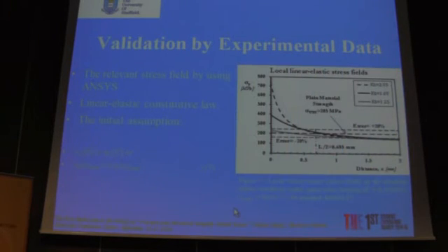From the linear elastic stress field in the vicinity of the notch, tested under quasi-static conditions for 6063T5, it is fully confirmed that the inherent strength could be taken equal to sigma UTS.